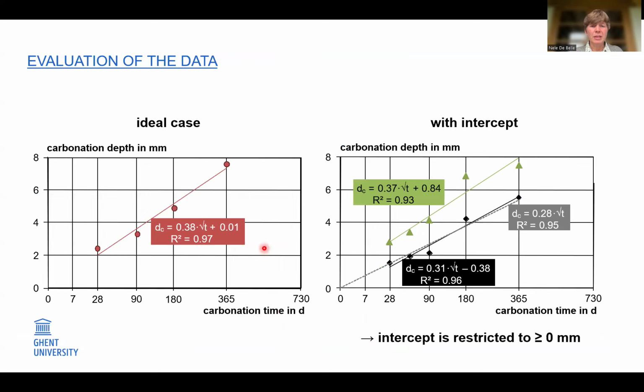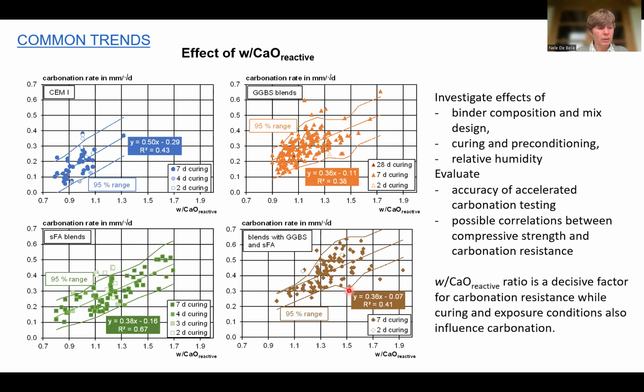For the evaluation of the data, we calculated carbonation rates based on the provided data points. If the obtained regression had a negative intercept, this was set to 0 because this is physically not possible. Now, the effects of the binder composition and the mix design, curing and preconditioning, and relative humidity on the carbonation rate were all evaluated, and also possible correlations between compressive strength and carbonation resistance.